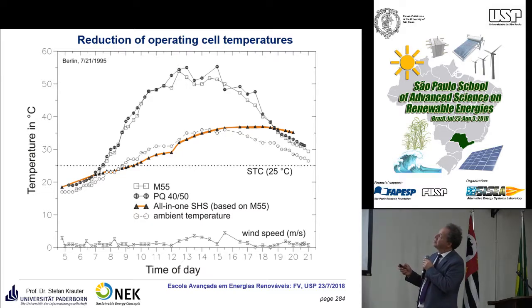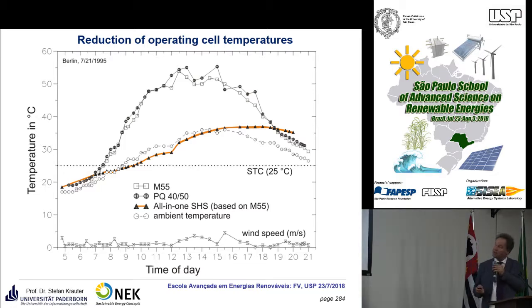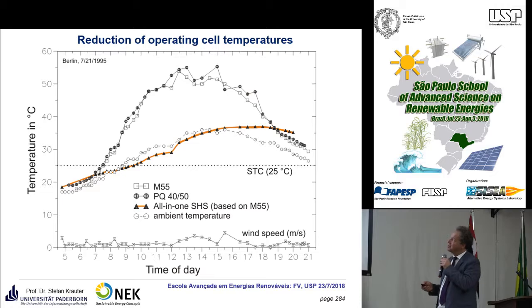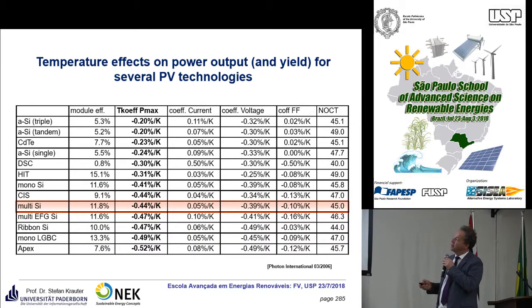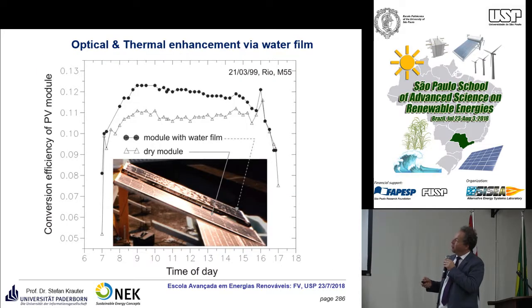So this is a conventional model with multicrystalline cells. This is one with monocrystalline cells. So this temperature is quite high. This is the ambient temperature here, and you see here the water temperature in the all-in-one solar home system is in the vicinity of the ambient temperature. So we have a significant reduction of the operating temperature, and this helps a lot for increased energy production. So we get about 8 to 10% more energy output by that system. If you consider the temperature coefficient, remember, then you get more efficiency.